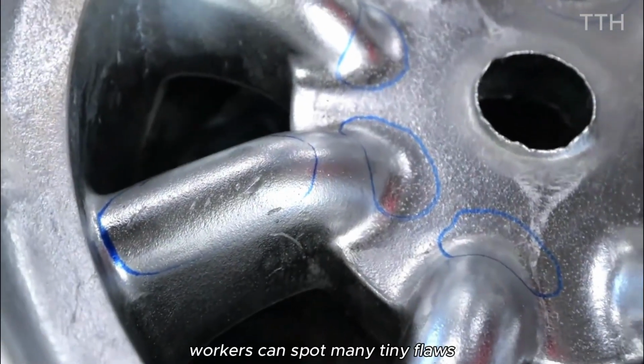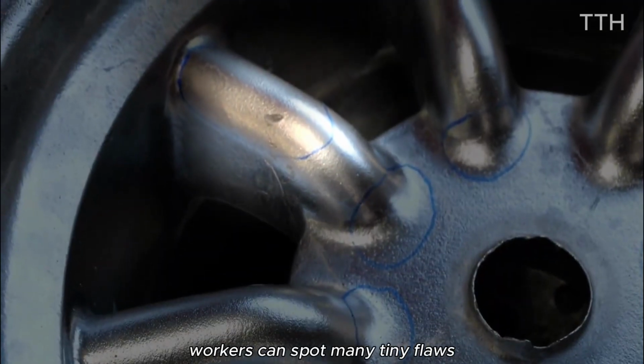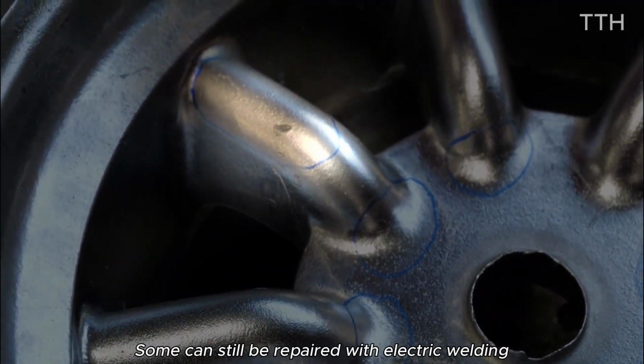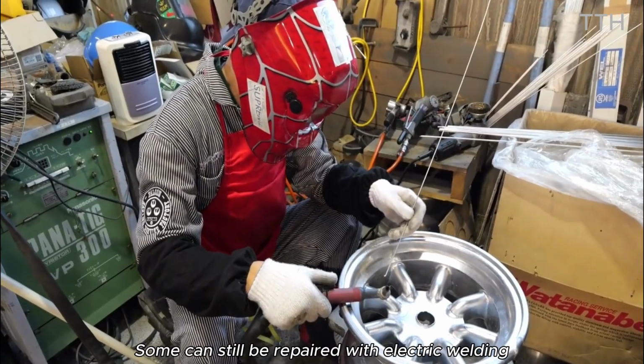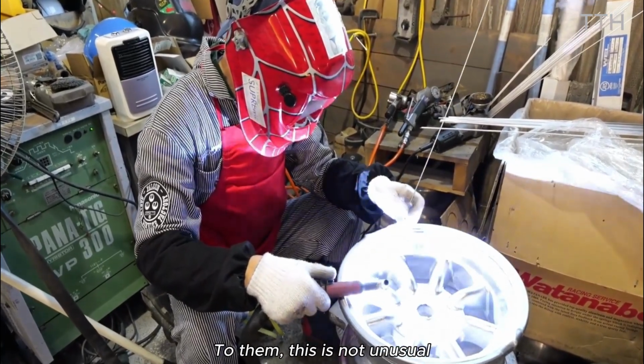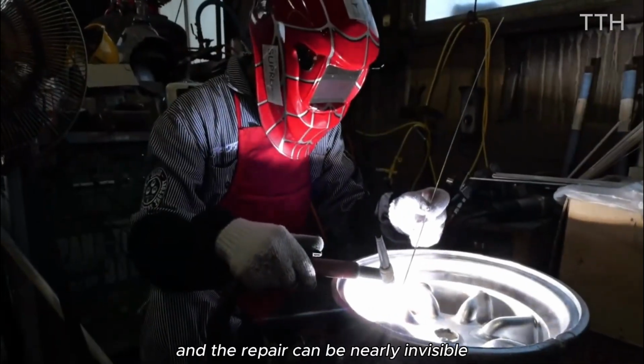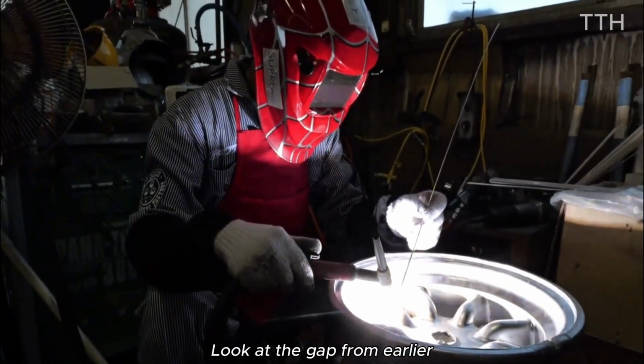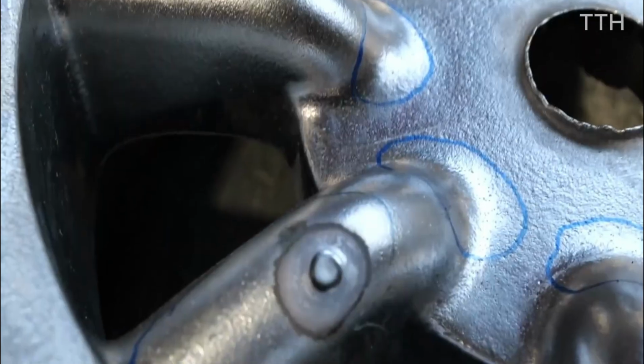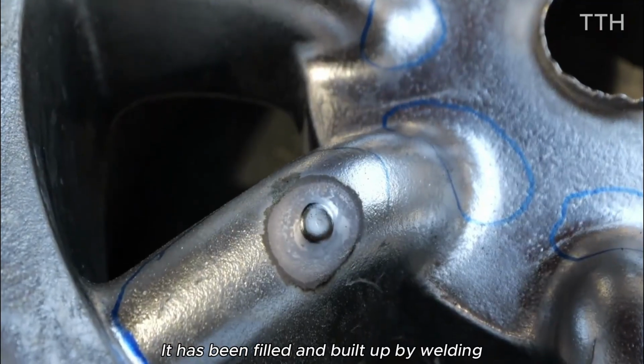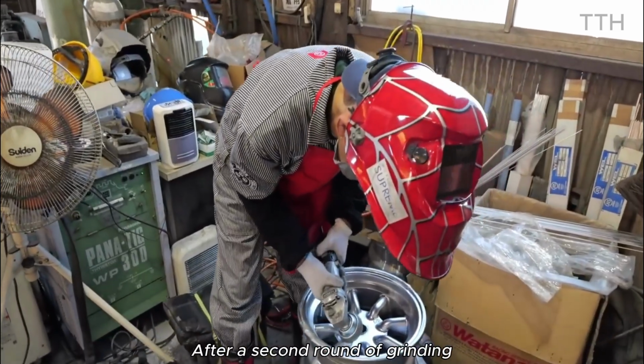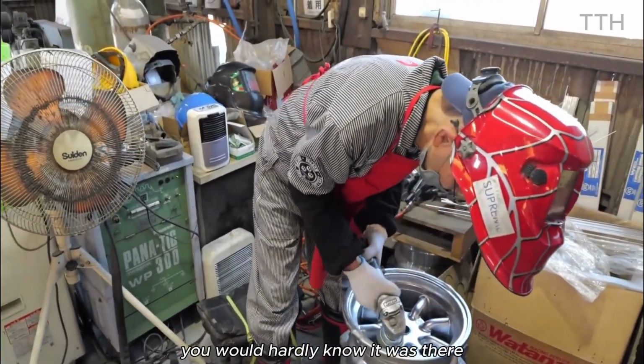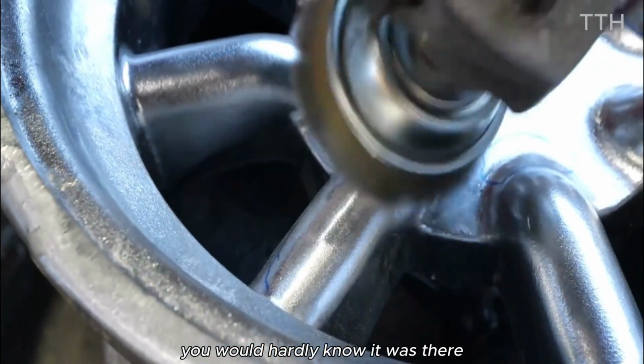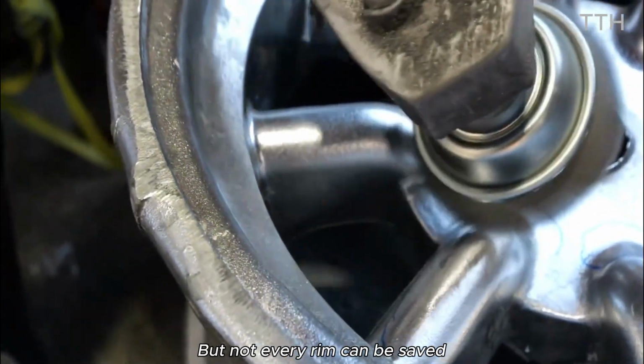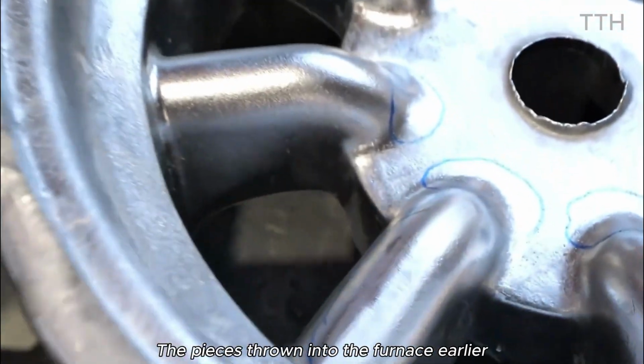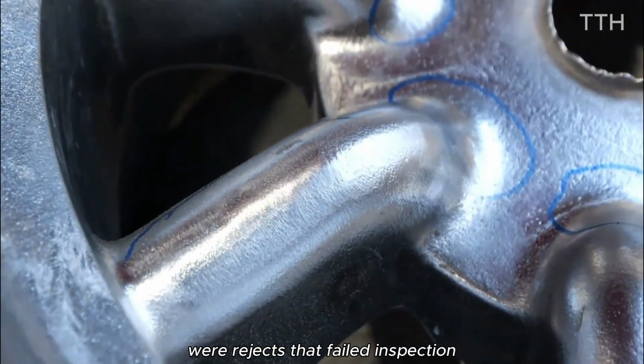During this step, workers can spot many tiny flaws. Some can still be repaired with electric welding. To them, this is not unusual, and the repair can be nearly invisible. Look at the gap from earlier. It has been filled and built up by welding. After a second round of grinding, you would hardly know it was there. But not every rim can be saved. The pieces thrown into the furnace earlier were rejects that failed inspection.